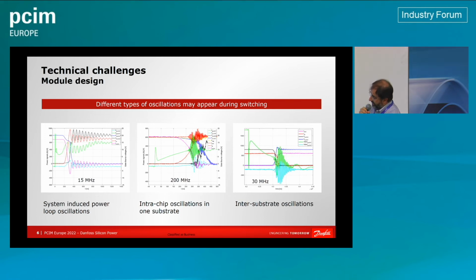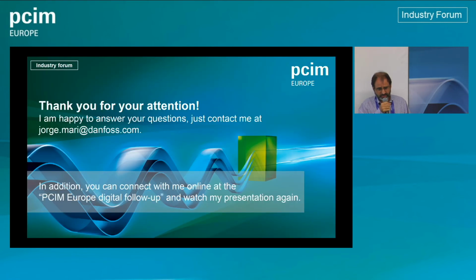And the other thing that you have to be careful of is also the inter-substrate oscillations. When you have more than one substrate in a big ampacity module, then this problem can happen not only between the chips in the same substrate, but also across the different substrates. And that's also something that one has to tackle early on, and which we do with the help of very detailed simulation models.